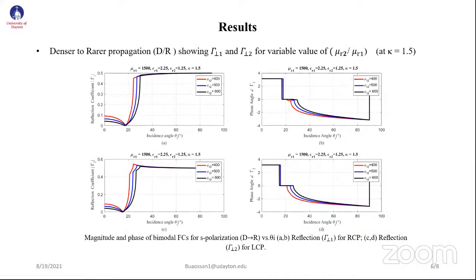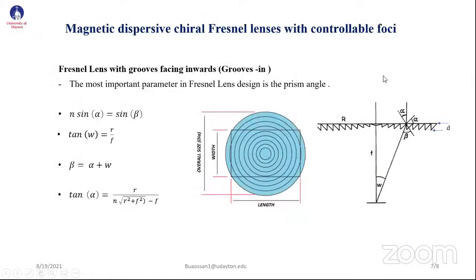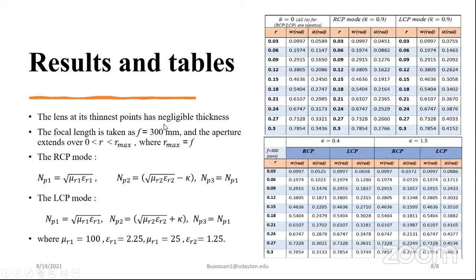This is by changing the chiral material itself: we change mu R2, that means we change the magnetic material of the second medium, and we make kappa 0. In that case, we studied some applications, one of them the slab and the thin film. Now we come to study the magnetic dispersive chiral Fresnel lens with controllable foci. That means we make the magnetic Fresnel lens itself chiral. These are the equations for the Fresnel lens, and we apply the incident angle to study its behavior, keeping the focal length constant.